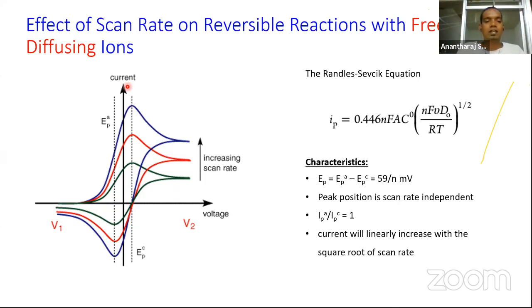But in practical electrochemistry, it is very, very hard to achieve 60 millivolt or close to 60 millivolt. So when you have a modified electrode and you believe that the reaction is completely reversible, you will always see peak-to-peak separation beyond this 59 millivolt. Researchers do agree that the reaction is reversible when the peak-to-peak separation is as high as 70 or 75 millivolt, but with the one condition that the peak position is not shifting. So this should be kept in mind.